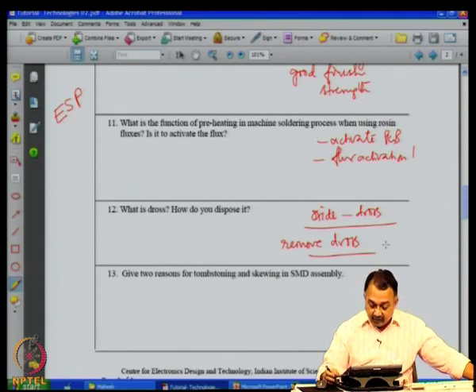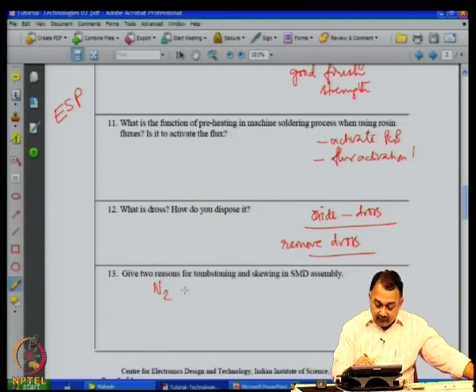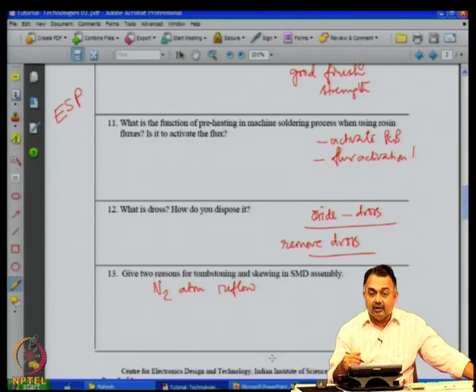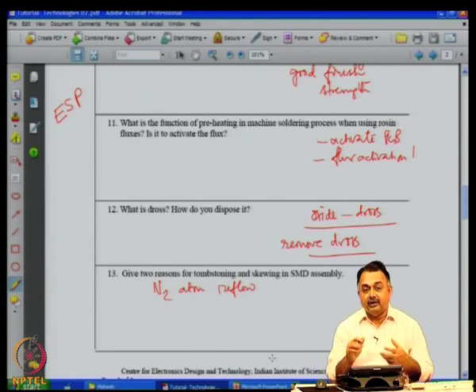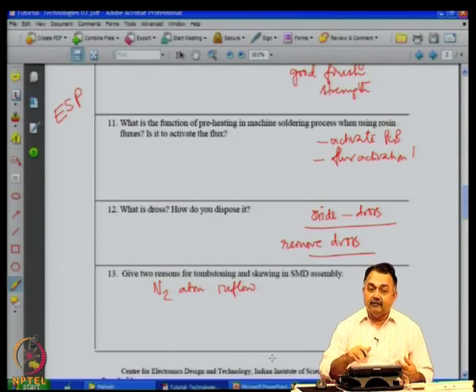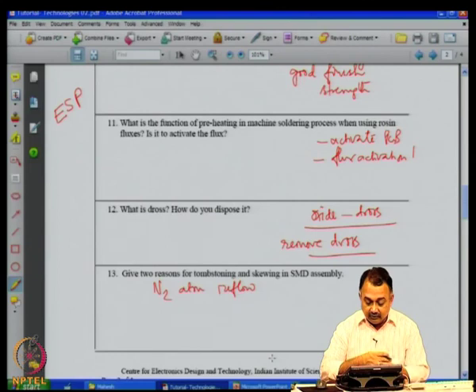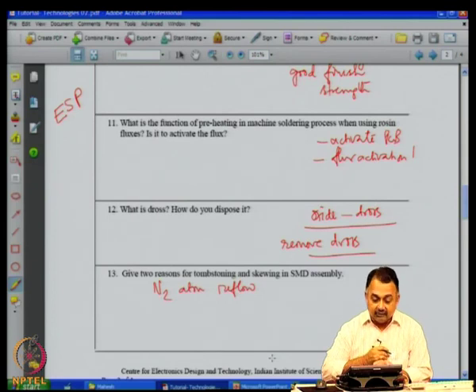Give 2 reasons for tombstoning and skewing in SMD assembly. As we have seen, if you are working in a nitrogen atmosphere in a reflow process, the different copper pads of, let us say, an SMD chip component could get different volumes dispensed, or there could be different temperatures on the copper pad, or the time taken for reflow could be slightly different between the two pads. That makes the force exhibited on one terminal of the chip component pull the entire component to its side, leaving the other pad open. So, this is tombstoning. Please refer to the SMT failure library that we have discussed.